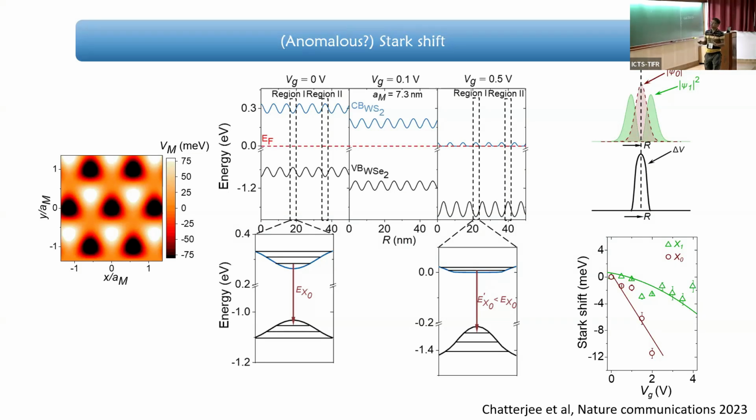But here, just because of a vertical electric field, we are able to obtain a sort of an even function of the potential delta V, and so we don't observe a quadratic Stark shift for the first one. We observe directly a linear Stark shift, which is exciting news because it can be stronger. On the other hand, this one is actually 0, but it starts showing the second order Stark shift. Okay, so that is something in contradiction with the typical quantum confined Stark effect.